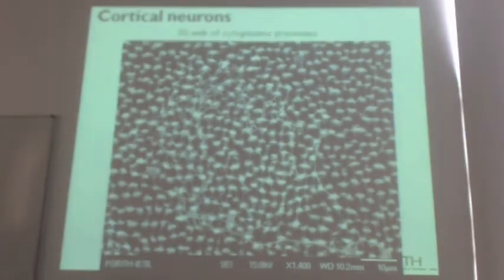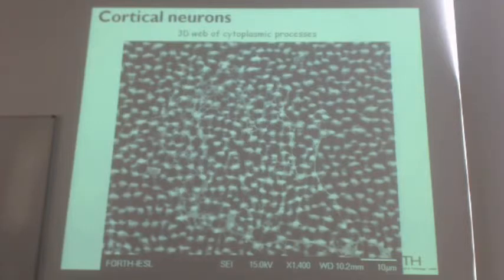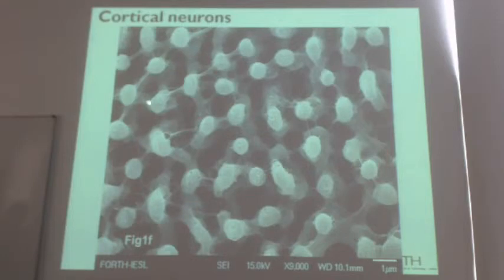But the most important observation we have here, and here the culture is in the absence of growth factors. There is no growth factor or ECM-based proteins that can promote the growth of neurons. You can see that we can observe a three-dimensional web of cytoplasmic processes, and actually this is indeed a three-dimensional web. You can see that these neuritic extensions can be grown at different height levels, from the top of spikes towards the base. As you can see here, some extensions on the top, in the middle, and on the base of microspikes.